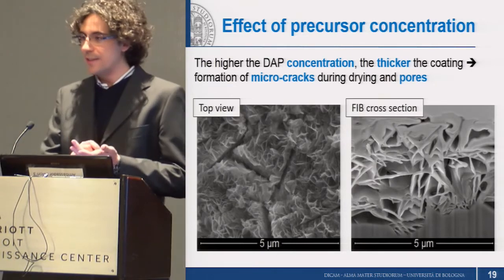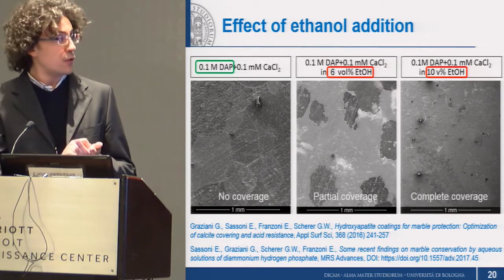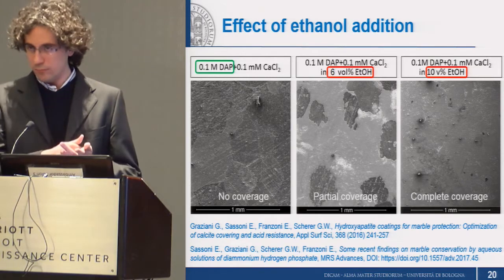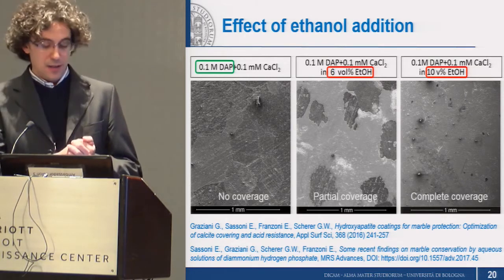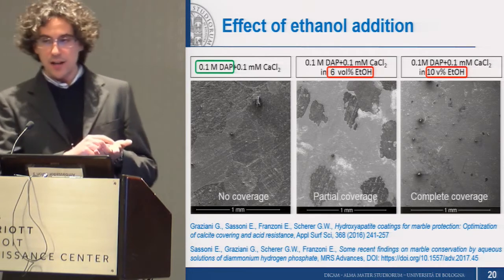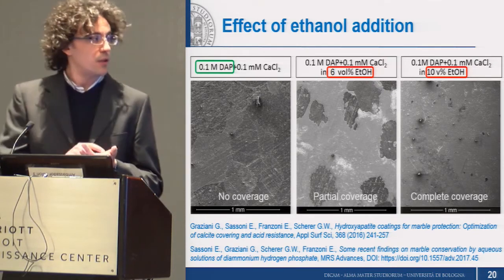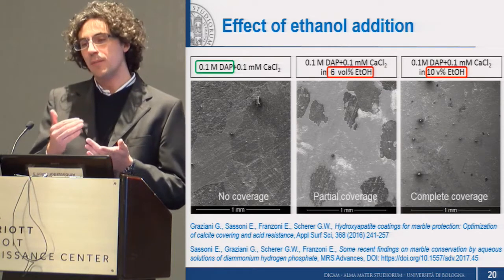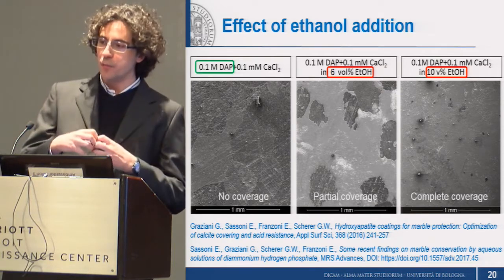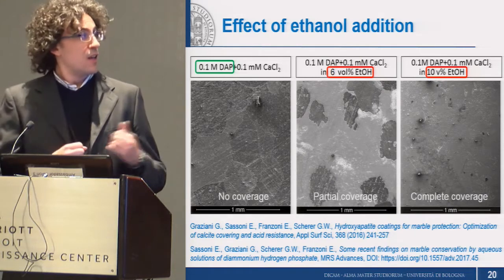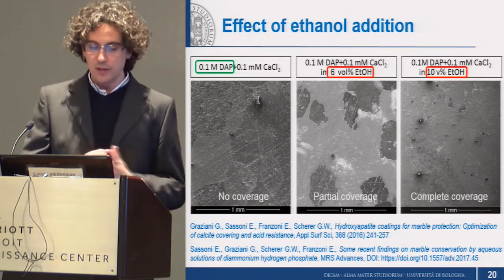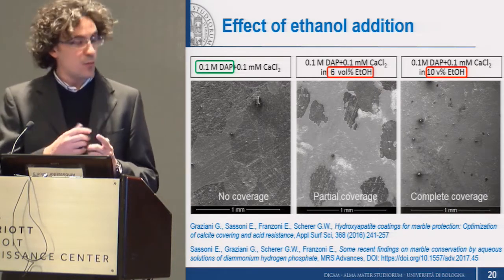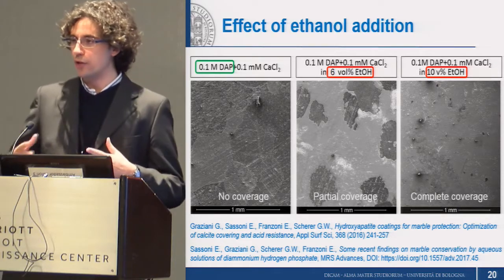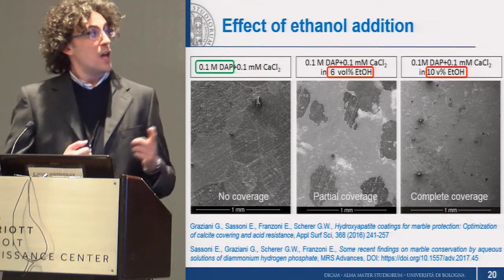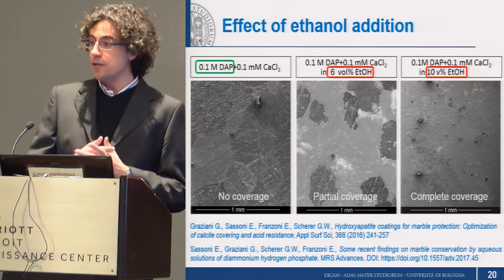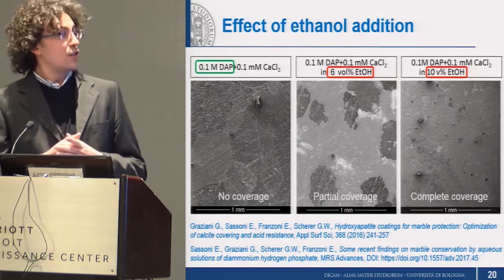to reduce the thickness of the layer, reducing the concentration is a potentially good way, because if we are able to create a layer that is as thin as possible, then because of thermodynamic reasons, it would be impossible for this layer to crack. So we tried reducing the DAP concentration, but at the same time we needed something to improve the coverage and favor HAP formation. And we found out that adding ethanol, so alcohol, has a very strong effect.